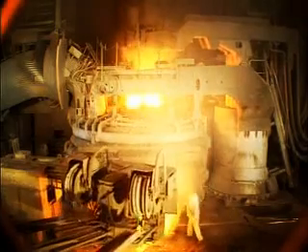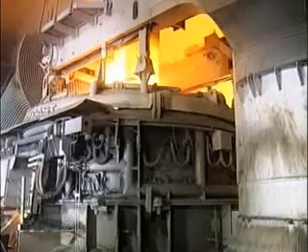When melting is complete, the furnace is tilted to pour off floating slag. The lance manipulator moves to its parking position. The steel is sampled and the temperature is measured for the last time. The electrodes are lifted and tapping starts. The Von Moos furnace uses full platform construction with a siphon spout tapping system. The furnace tilts to the tapping position, and after the 72 tons of liquid steel are tapped, the furnace returns to the horizontal position.